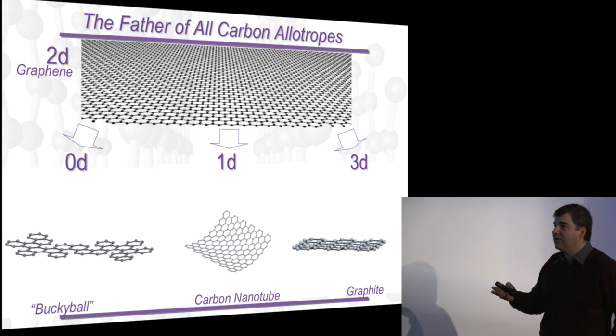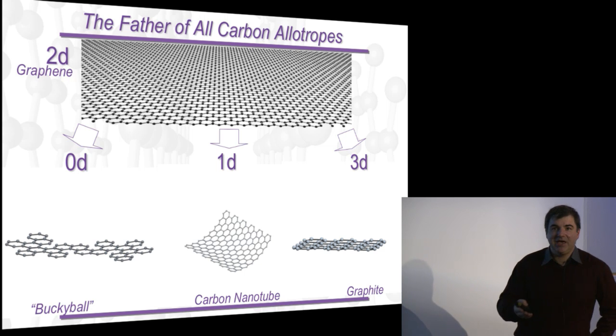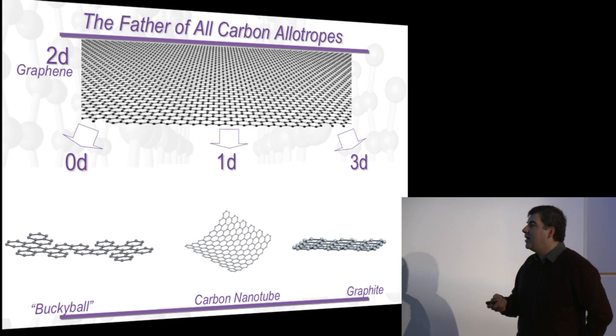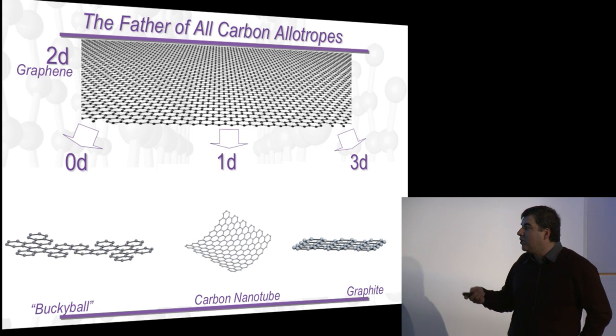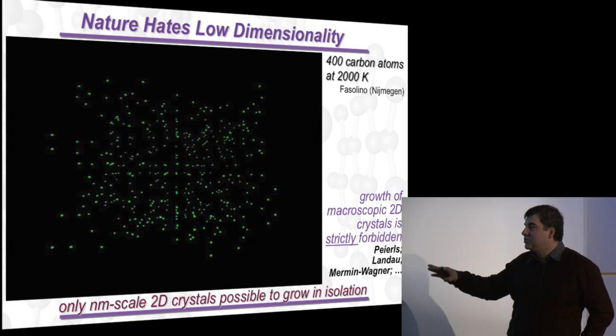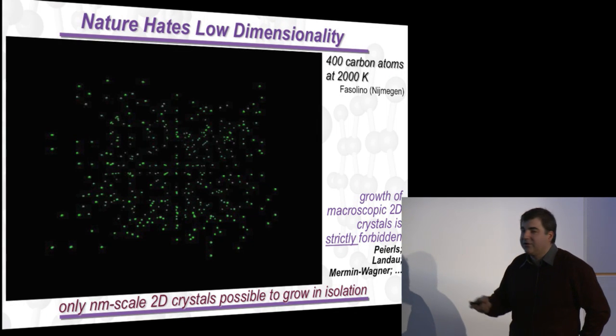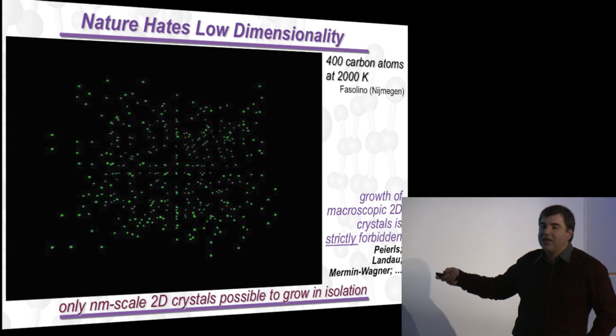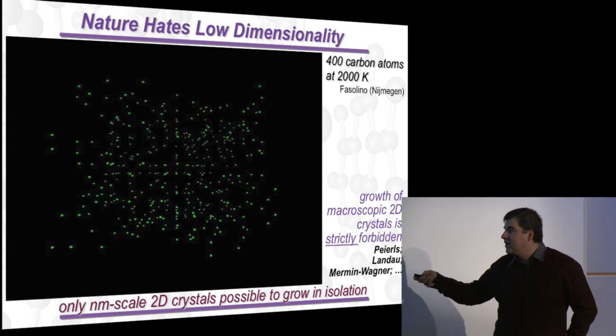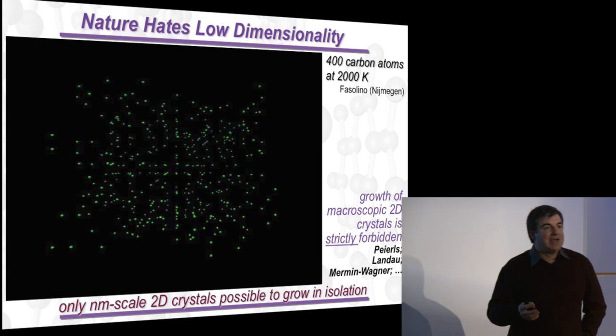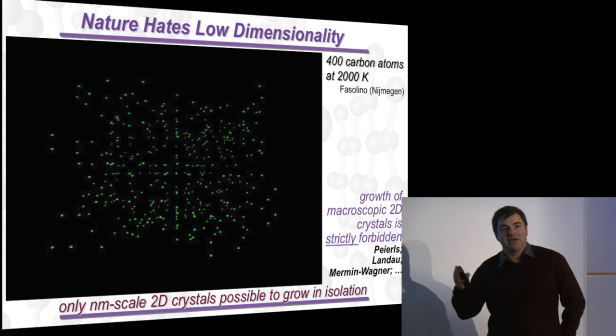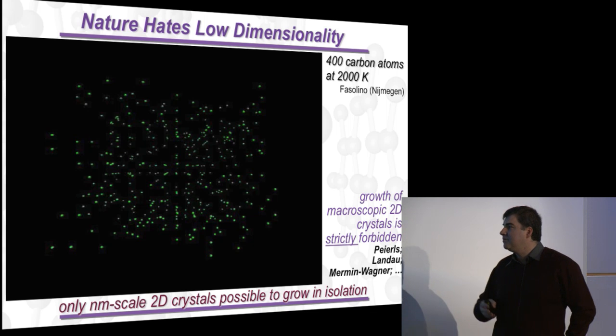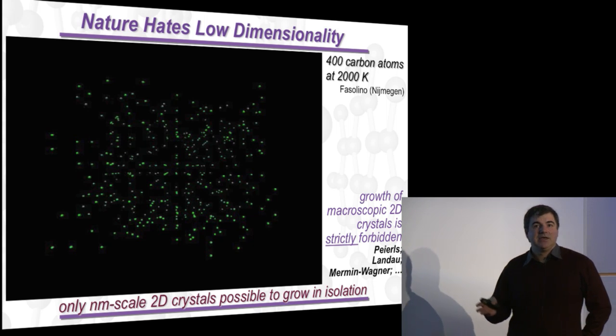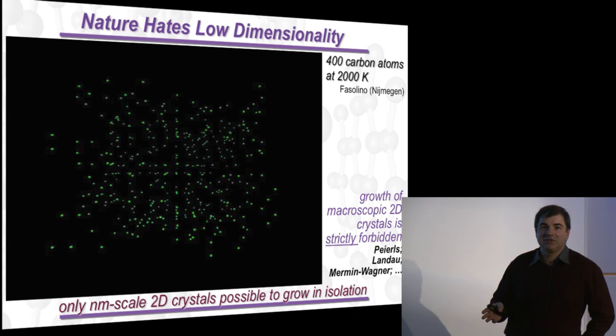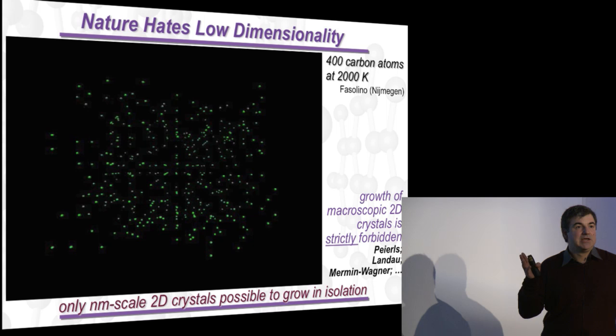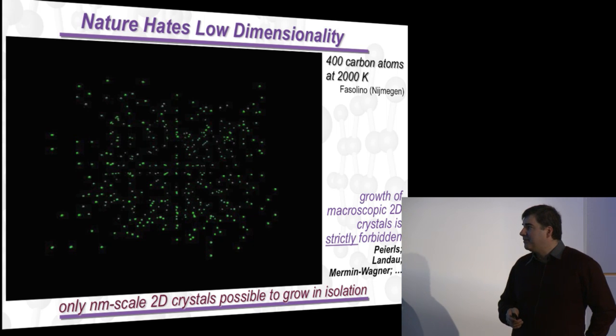So why is two-dimensionality so important? Well, it's because it's very hard to obtain two-dimensional crystals. So here is a model of 400 carbon atoms playing with each other at elevated temperatures. And sometimes they look like they're forming flat structures, but in fact, if you allow them to play for much longer, they will always come into some three-dimensional arrangement. There are many reasons behind that, like surface tension and the termination of the dangling bonds and so on, but there is one very fundamental reason: two-dimensional crystals or two-dimensional structures are not stable at any finite temperature. It's the so-called Mermin-Wagner theorem.